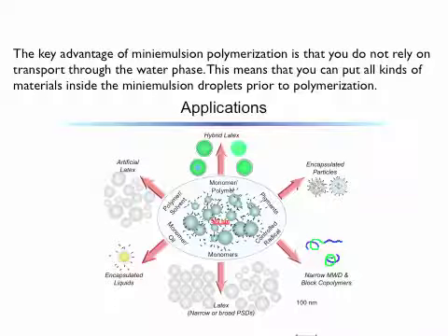So you can make artificial latex, which is, for example, really important in healthcare. They use this polylactic acid, and they have to make small particles out of this. So what do they do? They dissolve it in an organic solvent. They basically homogenize it with either ultrasound or with a high pressure homogenizer, and then they blow off the low boiling organic solvent, and then you have polylactic acid particles. And typically they put a drug in there as well, so you have a composite of these two. And those things are used in healthcare.